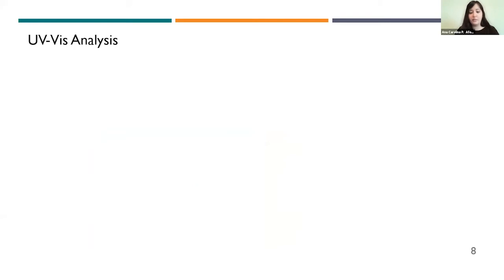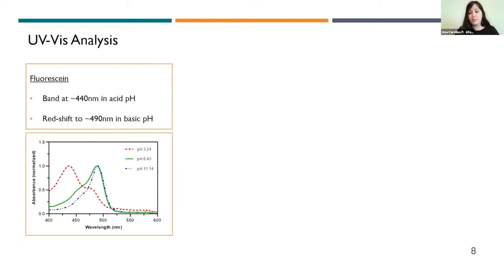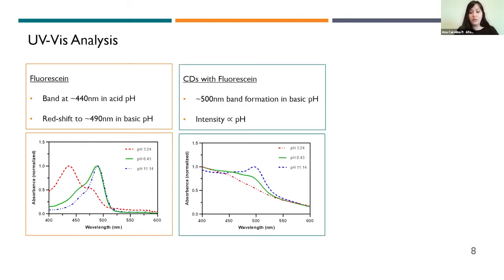We also evaluated the carbon dots' optical properties, and the UV spectrum of fluorescein and both carbon dots was analyzed at 3 different pH values. In the spectra of fluorescein, we found an absorption band at around 440 nanometers at acidic pH, which then redshifts up to around 490 nanometers with increase in pH. In the case of the carbon dot with fluorescein, while absent at pH 3.24, a small band is formed at around 500 nanometers at basic pH, and the intensity of this band appears to increase with pH. We attribute this band and its pH response to fluorescein-like structures in the surface of the carbon dot.